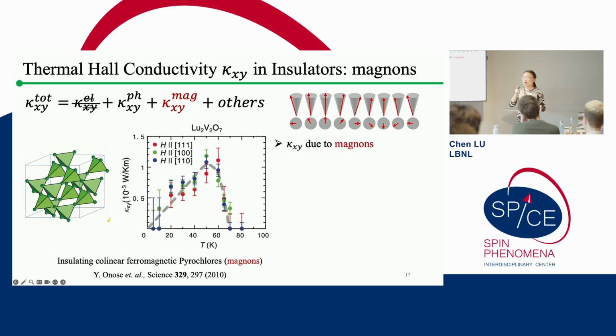I think in a previous talk, Carlo already showed this result, which is one of the most famous examples of a magnon thermal Hall effect, observed, I think, by Professor Tokura's group in the insulating collinear ferromagnetic pyrochlore material, lutetium vanadate. The reason why this result is extremely convincing that it's from magnons is because this material goes into the ferromagnetic ordered state below about 70 K. So when the temperature is higher than this magnetic transition, the thermal Hall effect is 0, and it only starts to grow to be non-zero when it goes into the ordered state. So this is the very first example of the thermal Hall effect coming from magnons in a ferromagnetic system.